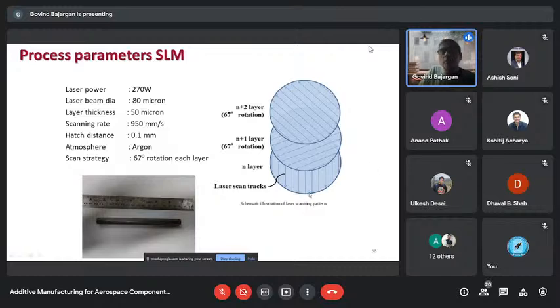So here, one more thing I wanted to inform is the scanning strategy. When the laser is scanned in a plane, say the nth layer, it goes scanning in this direction as shown here. The next layer scanning is turned by 67 degrees to the previous scanning direction. This change in direction actually provides isotropy in the properties. It removes the anisotropy in the deposit. So a study has brought out that if the orientation of scanning is changed by 67 degrees from the previous layer, and we keep on doing that, then we can control the anisotropy in the AM deposits.